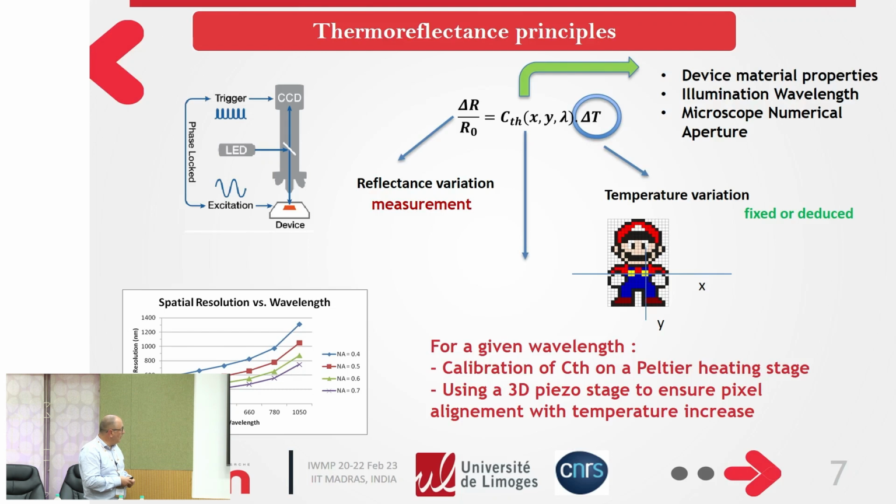But we also need to use a Peltier stage for fixing the temperature, and a 3D piezo stage to ensure the pixel alignment with temperature increase. Because when you apply a variation of temperature, if the pixel moves, you cannot ensure that the CTH you have measured is on the same pixel. So it's very important.